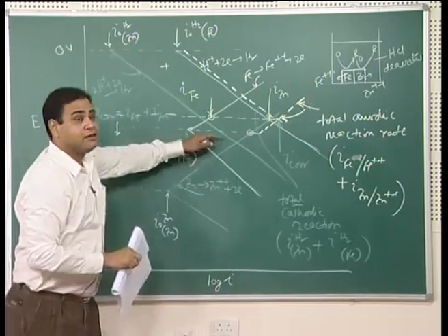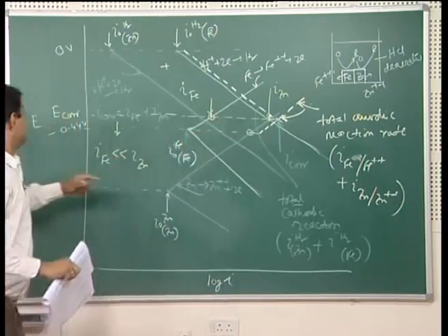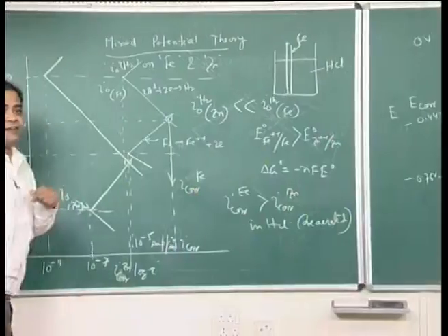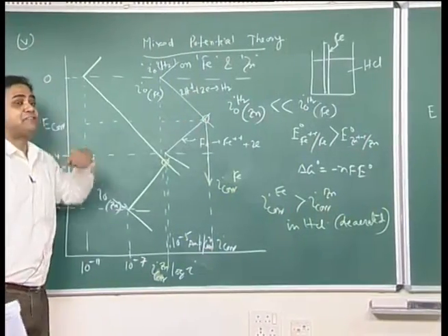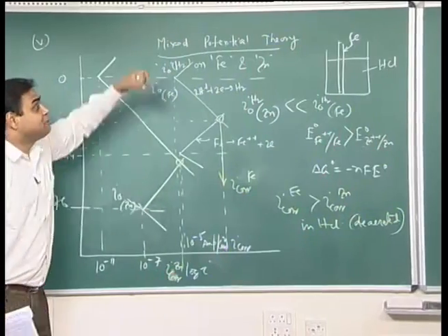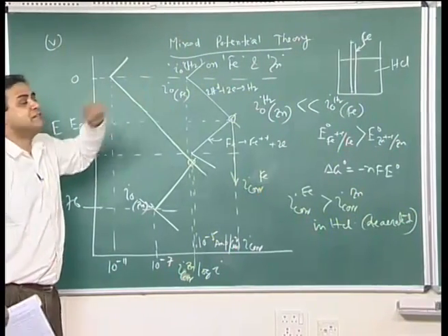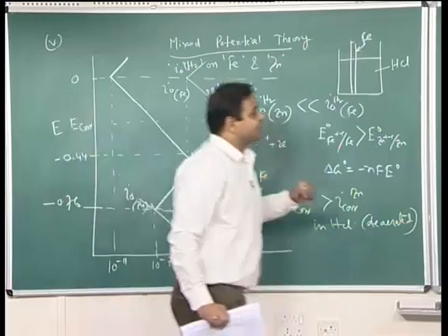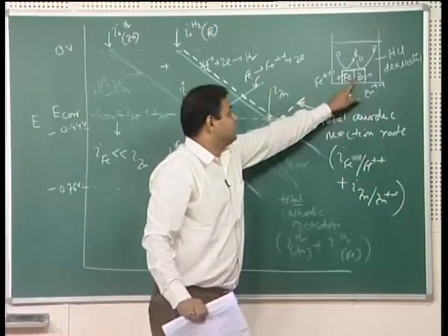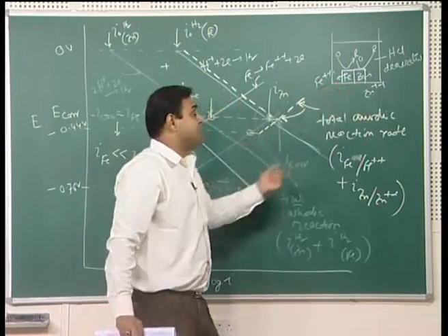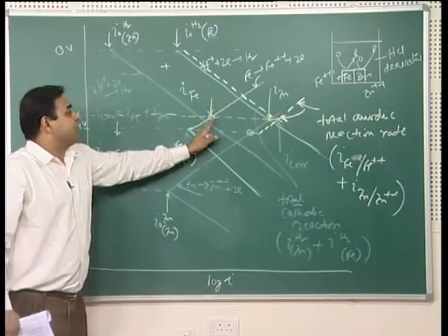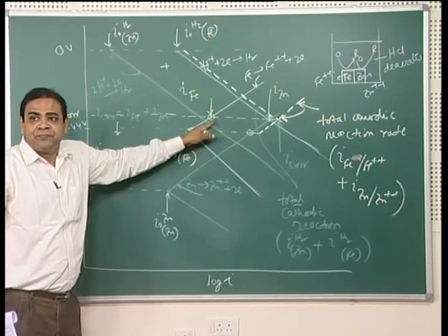This is interesting because now you see this plot and that plot. In this plot, iron corrosion rate is more than zinc if you dip these two pieces separately in HCl, but once you connect them at an equal area ratio and then dip them in HCl of the same concentration, you see that iron corrosion rate is decreasing, fine.